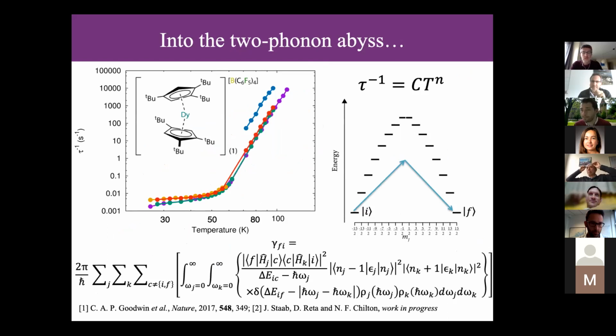Is there any particular symmetry that promotes or prevents this kind of two phonons process? I don't know yet. I don't think so, because the dominant contributions of these modes are the very, very low energy ones, because we are at such low temperatures that the occupations must be sufficiently high that you can de-excite. Because remember, this involves simultaneous excitation and de-excitation of two different vibrational modes. So you must have an excited vibrational quantum of one mode in order to see it. And so this process is dominated by the very, very low energy phonons, because they have near zero energy, non-zero occupations, even down to absolute zero, right? So that's why it's dominated by low energy phonons.